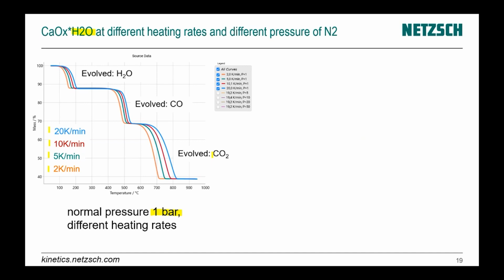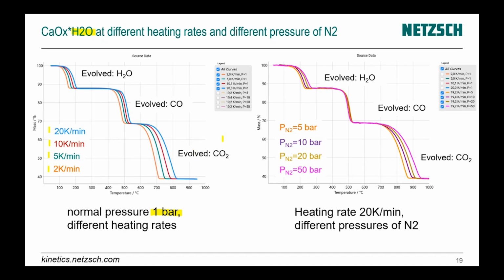Here is the classical kinetic evaluation for different heating rates, where we have only temperature as a parameter. And now let's see what happens with a high pressure of nitrogen, of inert gas. Here we have several measurements where we have always the same heating rate, 20 K per minute. And here we have different pressures of nitrogen, 5, 10, 20, and 50 bar. We can see that the first step with the release of water is pressure dependent. And for the higher pressure, we have decomposition at higher temperature. So with higher pressure, the reaction will be moved to the higher temperature.